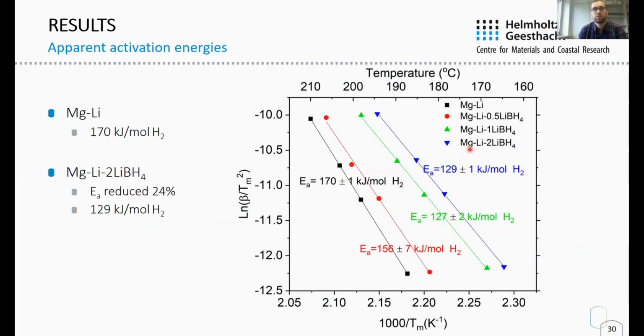In order to evaluate the effect of the addition of lithium borohydride on the activation energies of the samples, I calculated again the apparent activation energies using DSC measurements applying the Kissinger method. Activation energy for the pristine sample is found to be around 170 kilojoule per mole, and addition of lithium borohydride clearly reduces the activation energy. For example, for adding 2 moles of lithium borohydride, it is reduced by 24% to 130 kilojoule per mole. Possibly the reaction of lithium borohydride with the sample leads to the formation of a new compound, and the presence of this compound leads to lower activation energy.